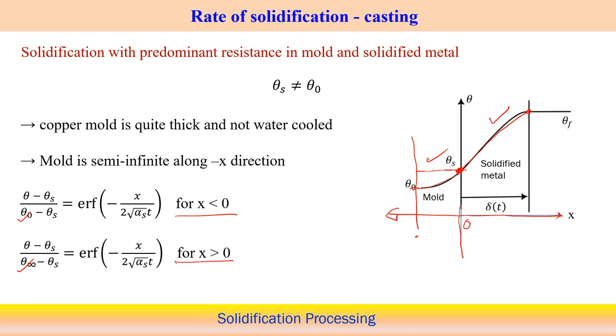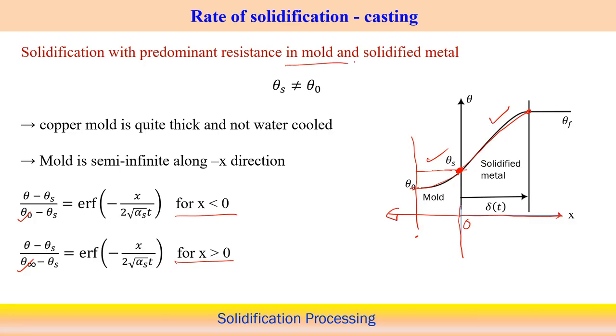we can find out. So when you start the solidification with predominant resistance in the mold and solidified metal, that means contact resistance from both the mold wall as well as the solidified metal, we can consider both the component resistances, and we take this as a reference point, with positive x and negative x. In these two cases the temperature distribution is like that: (theta minus theta s) by (theta 0 minus theta s) equals error function of minus x by twice root of alpha s into t, that is true for x less than 0.